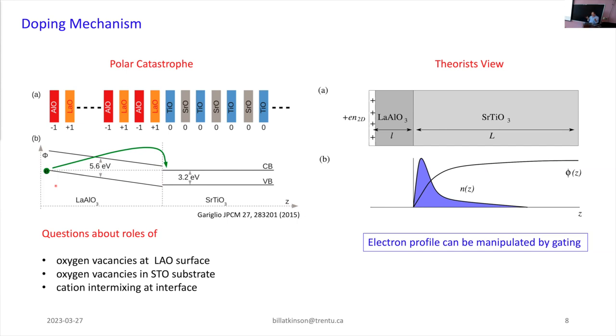And so this happens in other polar materials, but typically, if something has to give, what gives is you get an atomic reconstruction. The surface of your material reconstructs in such a way as to relieve this growth in the potential. Here, it seems that the lanthanum aluminate is stable enough that this doesn't happen. And instead, well, the cartoon at least is that you get a transfer of an electron from the valence band of the LAO into the strontium titanate. In fact, it's probably more complicated than that. Probably the charge transfer is mostly coming from oxygen vacancies at the LAO surface rather than from the valence band.